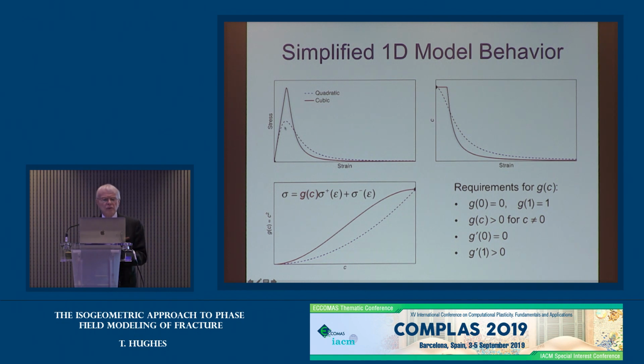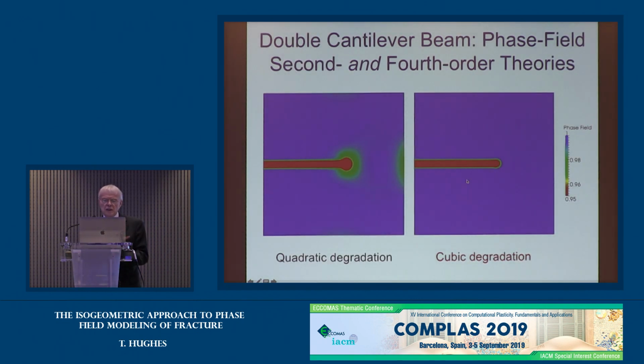So very quickly, if we look at the picture, this is the stress strain diagram. This is the picture I just showed you for the phase field itself. And this is the stress degradation curves right here. Now, this is sort of like getting started here. If you move a little bit, you see what happens. You just stay here, and then you drop down for these different states. So you're here, you're about to turn. Here, you're already exhibiting some damage. And then you can run through the cycles and see what happens. So if you use that theory, it behaves as advertised. It essentially gets rid of all of this diffuse damage, which is really spurious.